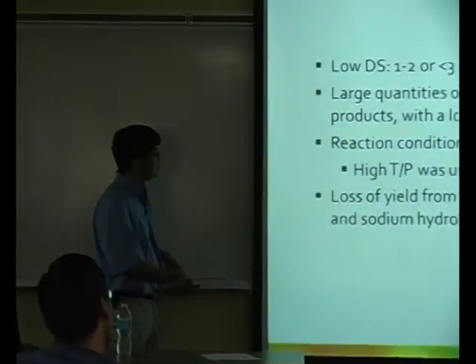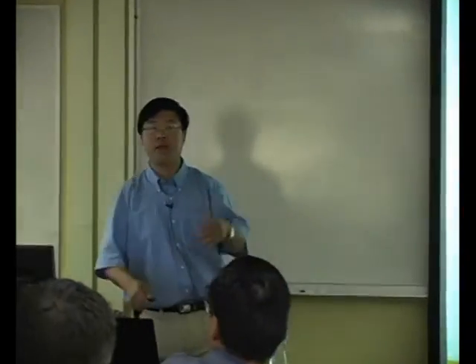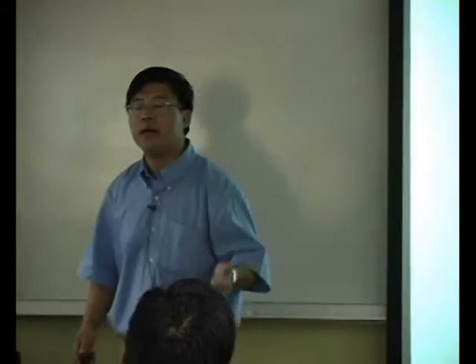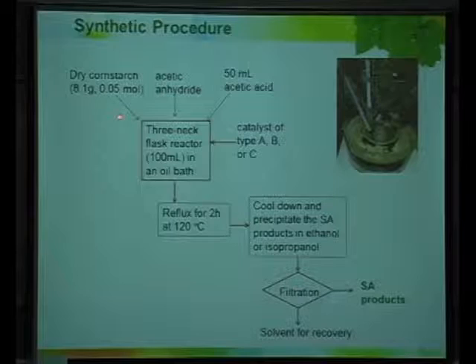And there is a loss of yield because of hydrolysis, because they use a sodium hydroxide catalyst, and this catalyst can hydrolyze the acetic anhydride, the reactant, which makes this whole process not that high yield. The efficiency is low. So now we want to propose a new process that uses new catalysts.